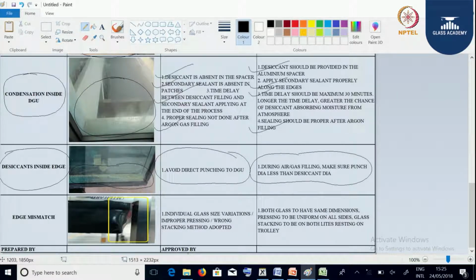Next defect you can see is the edge offset. You can see with the right angle there is an offset of the edge in the figure. This is due to individual glass size variations, improper pressing, or wrong stacking method adopted. We can overcome this issue by ensuring both glasses have uniform dimensions, pressing is uniform on all sides, and glass stacking is uniform, resting evenly on the trolley.